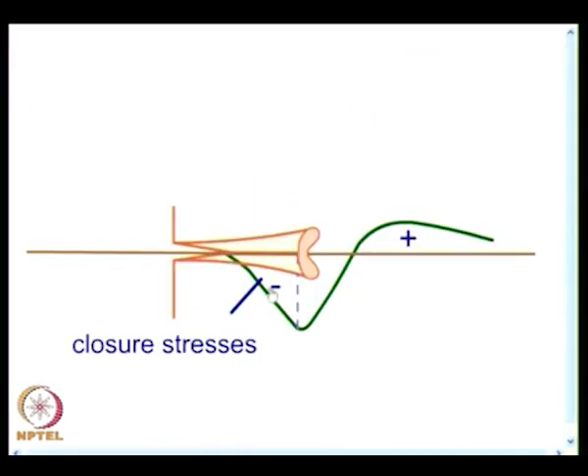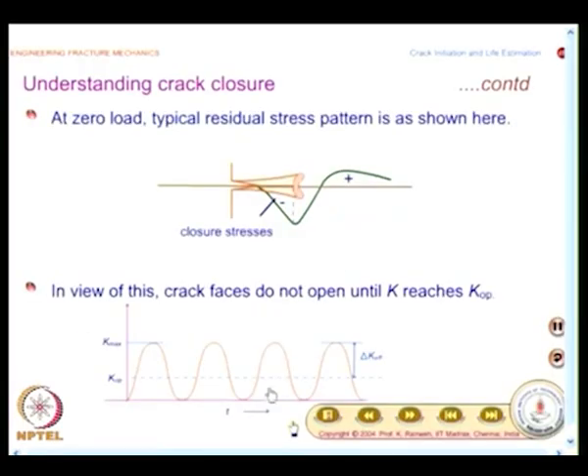So, I have this as closure stresses, and you have a residual tension here, and because of this the crack surface is closed. This needs to be appropriately modeled in your dA by dN calculation, and that is what is given in the next slide. In view of this, the crack faces do not open until K reaches